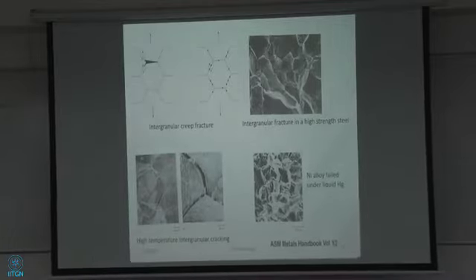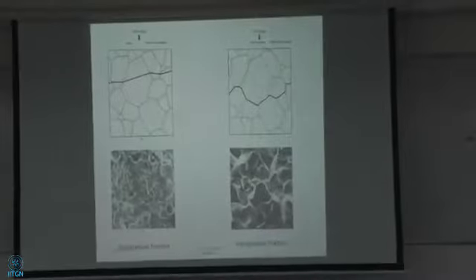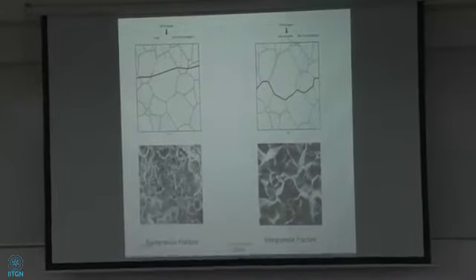So you will encounter this intergranular type of fracture. What this means essentially is that somehow the grain boundaries have gotten weakened. That's why it prefers this fracture mode, because the cohesive energy between the boundaries has reduced, so they open up more easily. Have you ever taken mica sheets? If you put a drop of water, they will separate more easily. The drop of water will decrease the cohesive energy between those mica sheets. We used to play with that when I was in college, I remember. You can separate the sheets out real easy because you're reducing the cohesive energy.